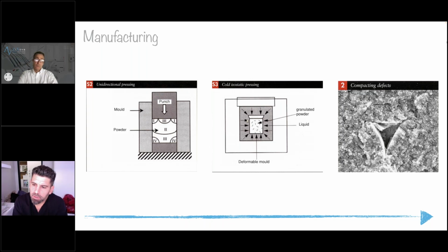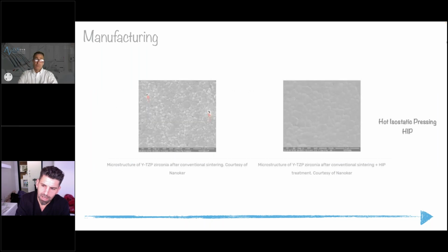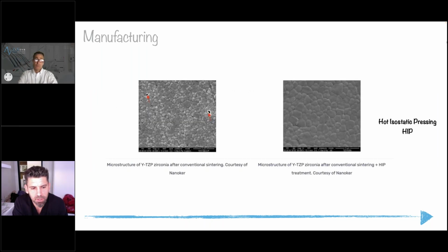But both of these methods left what's called compacting defects. And as you can see here, you'll have these little pores or these little holes. And this was the weak link in this manufacturing process. And that's why we saw some of these fractures. Now, this evolved to what we now know as hot isostatic pressing. And this is what I would say 90% of the implants that we have in the market today are manufactured by hot isostatic pressing. And this eliminates these voids or these gaps that were happening during the compaction process.